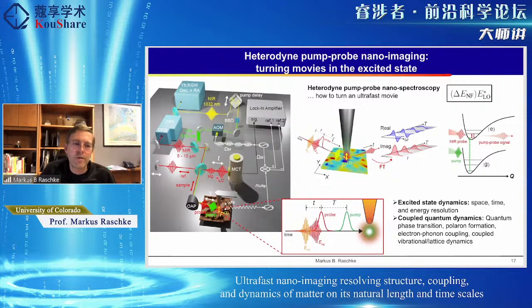And this allows you then to heterodyne amplify the signal field, and then also through this interference between the signal and the local oscillator, measure an interferogram of this excited state dynamics, and then get the spectral information by Fourier transforming the signal. And then the tip-sample distance is modulated, the pump-probe delay is varied, the pump pulse is modulated, and the reference field. And if you have a brilliant enough grad student and postdoc who can still keep the overview as these signals are fed into the detector electronics, then you can actually separate the desired signal.